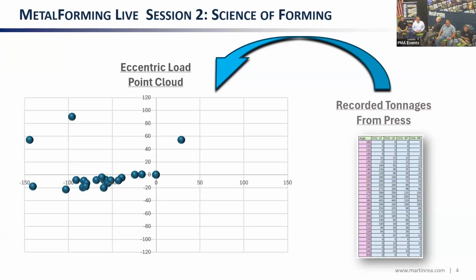And you can see that the vast majority of the points are not at 0, 0. When you look at the press tonnage curves from the manufacturers, what they give you is that our press is worth 3,000 tons at bottom if the load is being applied at the center of the press. It's quite obvious from the positions of the dots on this diagram that loads are being applied outside of 0, 0, and we need to be cognizant of the load placement on the bolster, and of how high up in the press stroke that load is being applied.